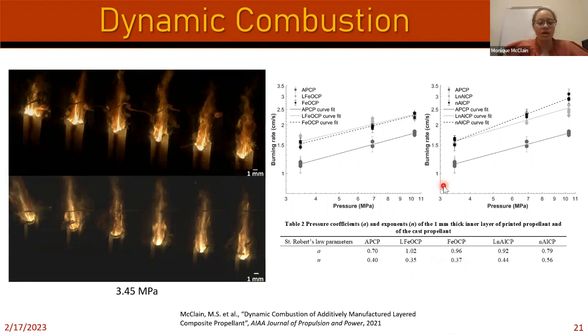However, when we look at this nano aluminum data, this curve is the same as this curve on that plot. So again, the slower burning layer. And the black represents the burning rate of just nano aluminum based propellant, so no layers, just by itself. And this lighter gray is the burning rate of this middle layer here. What we found was this middle layer actually does burn slower than the normal nano aluminum by itself. You can see 0.44 versus 0.56. So the question was, why is this burning a little bit slower here at this middle part?